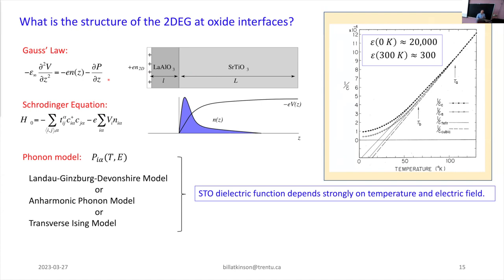To get the electron density, I solve Schrodinger's equation. And here I've just got a tight binding model. When you electron dope the strontium titanate, the electrons go into the titanium atoms. The titanium d orbitals have T2G symmetry. So there's a dxy orbital, a dyz orbital, and a dzx orbital. So I have three types of orbital here. And that's all I've got. That's the only interaction I have there. Plus, I have the electrostatic potential that I've solved for from Gauss's law.